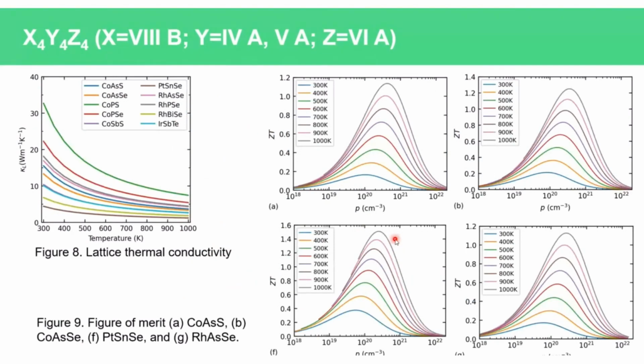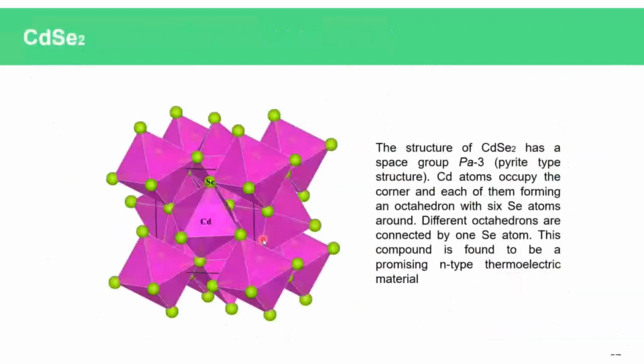However, we also found that this group of materials have high lattice thermal conductivity, as this picture shows. Due to that, the maximum figure of merit of those compounds is not much higher than those state-of-the-art thermoelectric materials. So for this group of compounds, the most important way to improve their figure of merit value is reducing their lattice thermal conductivity, which can be achieved, for example, by alloying among these compounds.